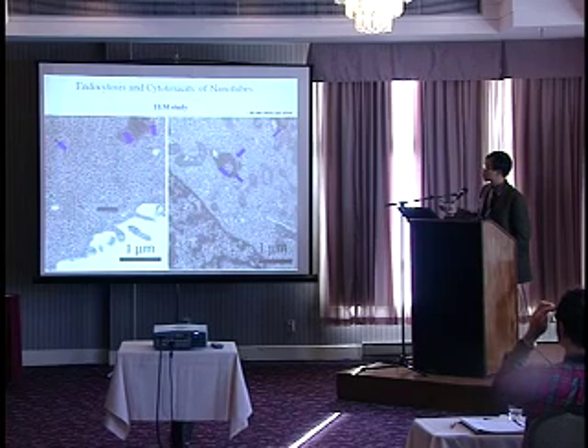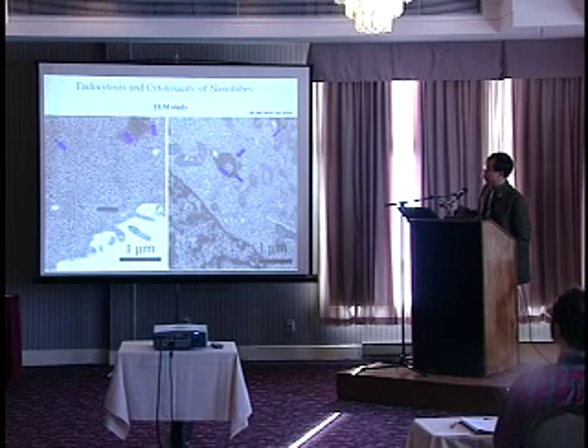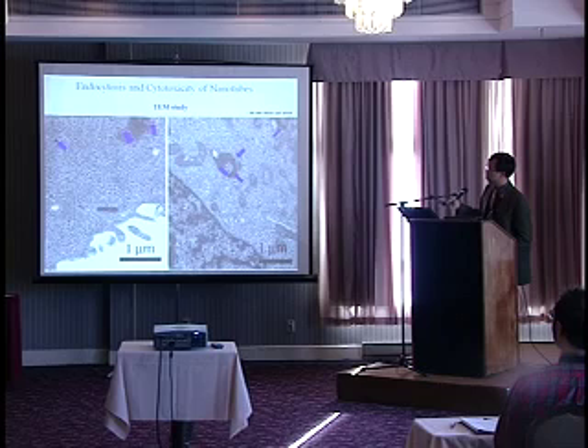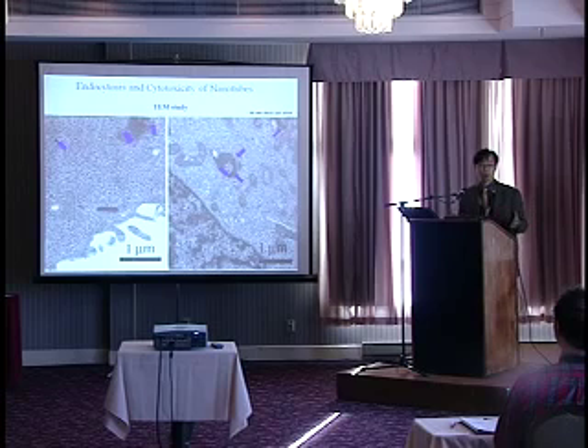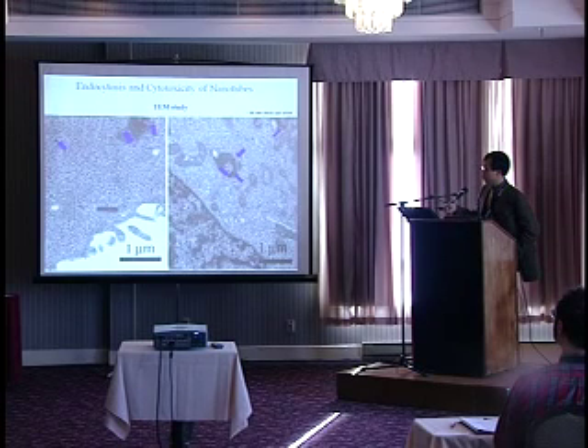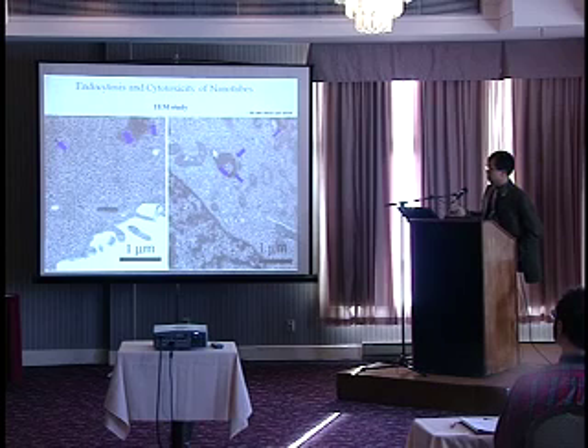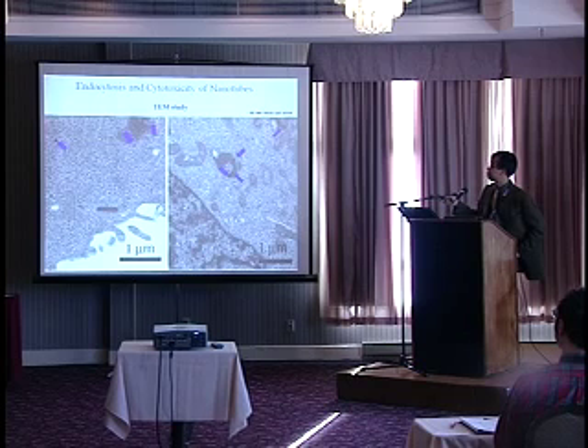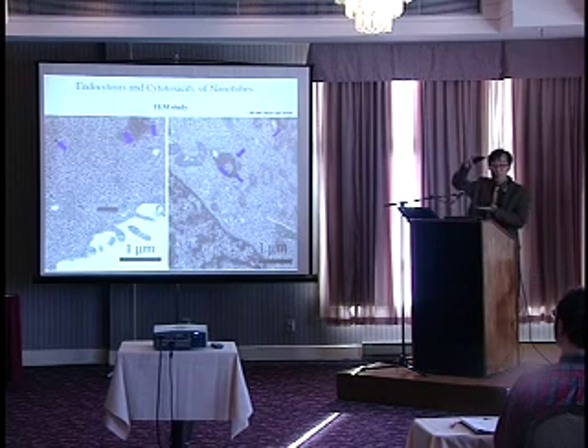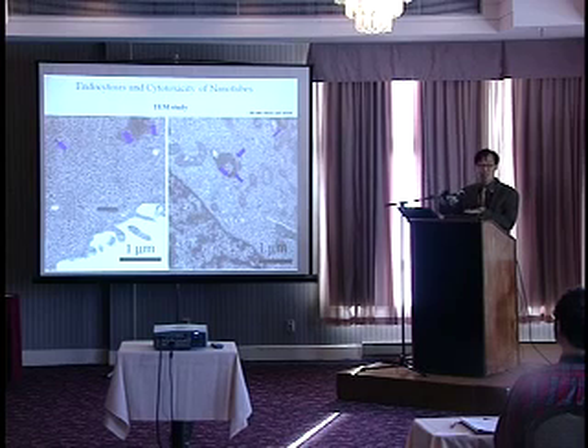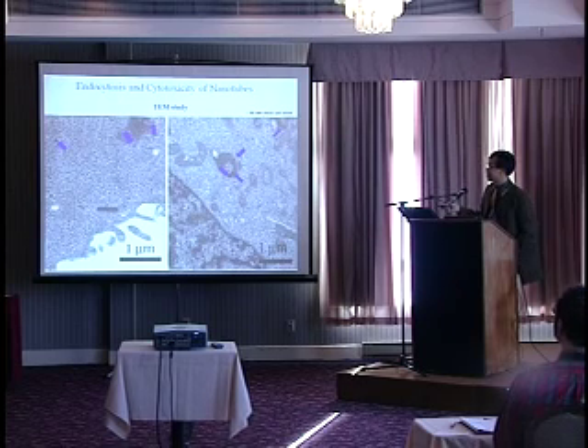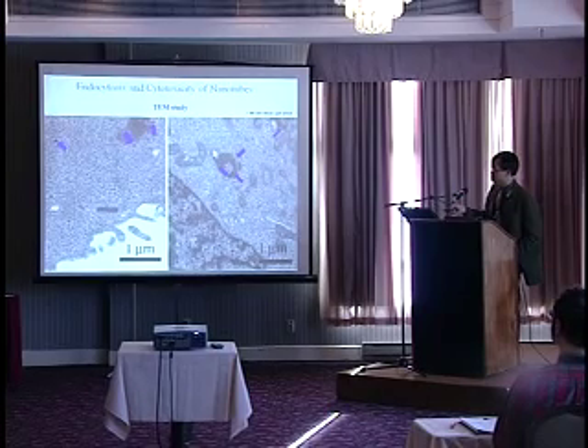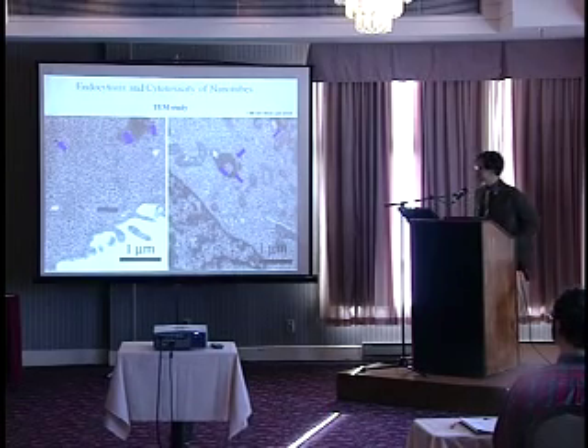This is the TEM image that shows that in the cells, you see these individual nanotubes here. The good news is that some of them are found in the cytosol, which is good news for drug delivery. And there is one laying-down nanotube, which is extremely lucky in this case. The thickness of the cell slice is 60 nanometers, so when you cut it, most nanotubes should show this kind of circle. But certainly, we were lucky to see this laying-down nanotube here.